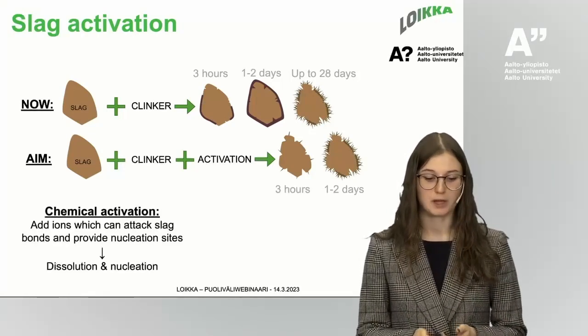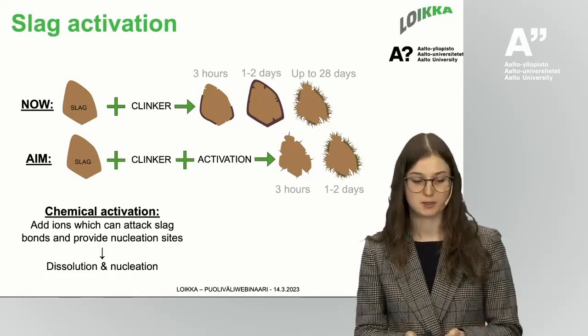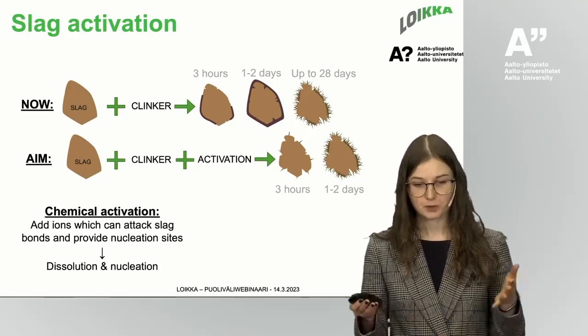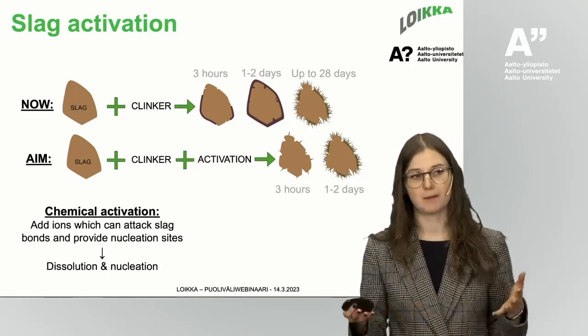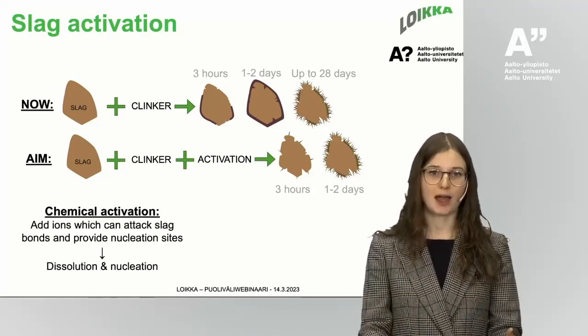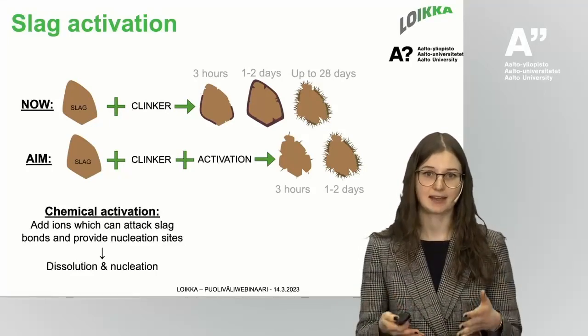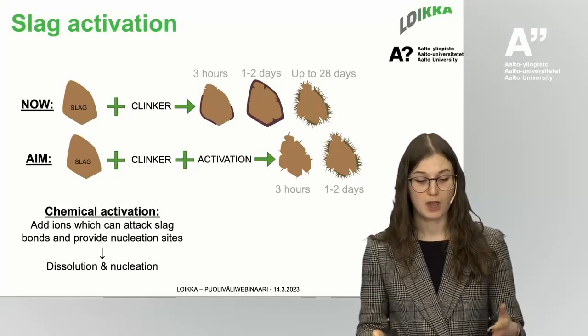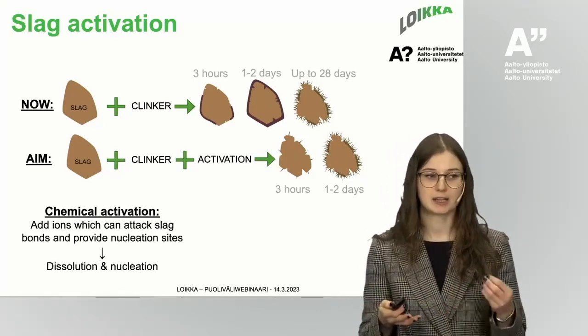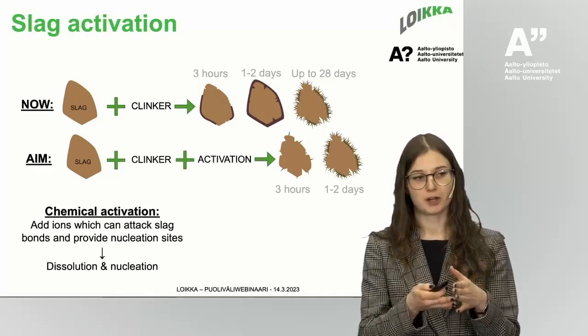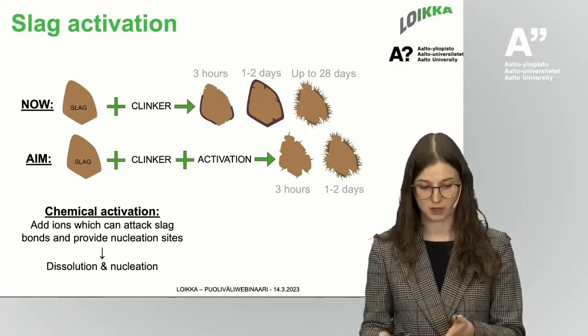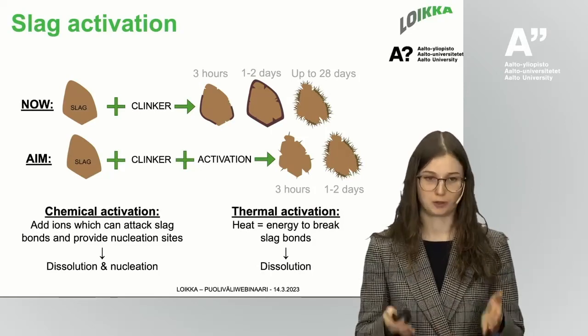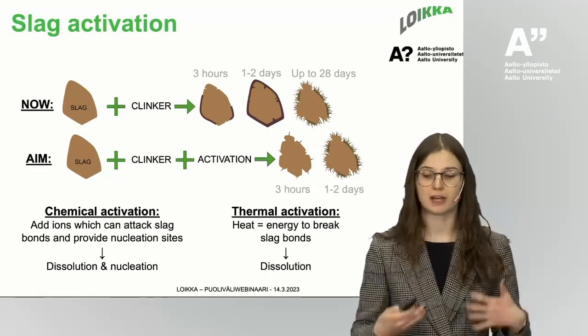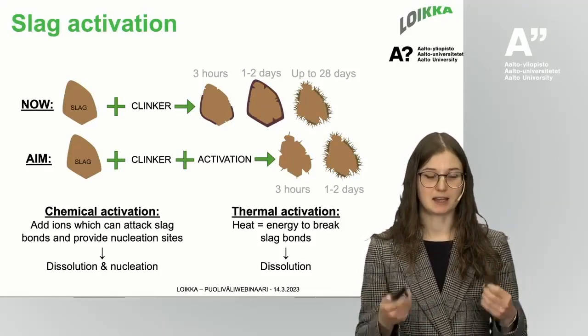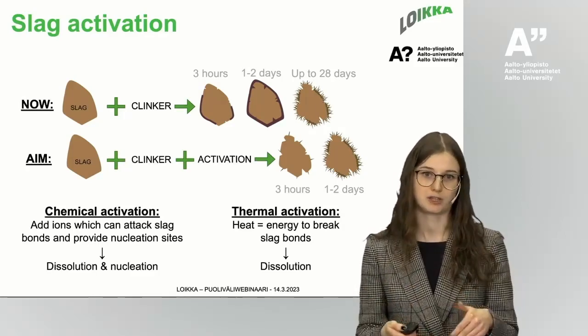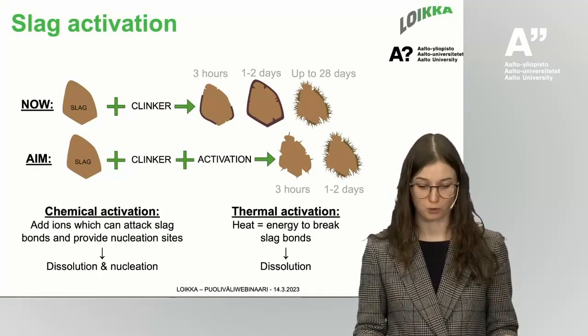For that purpose, we're using two main activation methods. One is chemical activation, which means that we add, usually in a liquid state, some chemicals that produce additional ions in the water that can more aggressively attack slag and force it to dissolve. There is also another group of chemicals that provide surfaces for hydrates to grow, and that will affect the nucleation. Another mechanism that we want to try is thermal activation. The idea is that we're providing heat into the system, and this heat gives energy to the water molecules, and the water molecules start attacking slag more aggressively, also forcing it to dissolve.